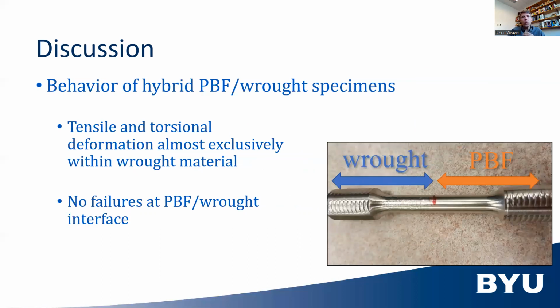For our hybrid specimens, which is really what we were concerned about, we wanted to find out if we were at least as good as the original material. We didn't want our additive portion of the part to shear off from the original substrate and have that failure at the interface. But we found that we did not have any failures at the interface. Almost all of the failures and deformation occurred within the wrought portion of the part. So because we saw that the wrought material was a lower strength than the PBF material, almost all the deformation was limited to that side of each specimen.